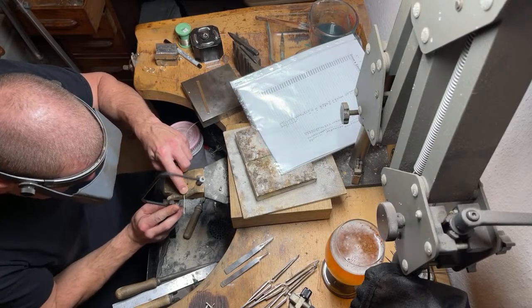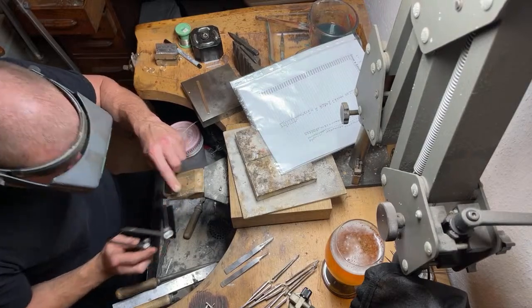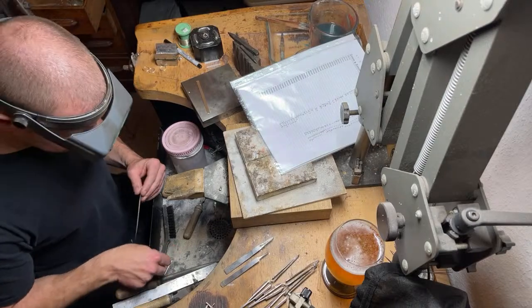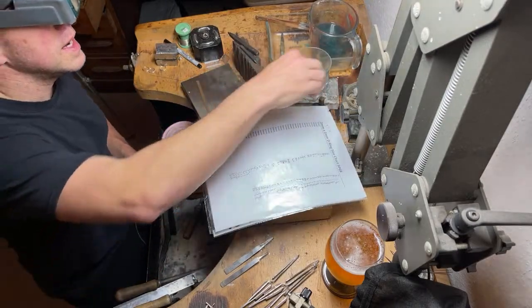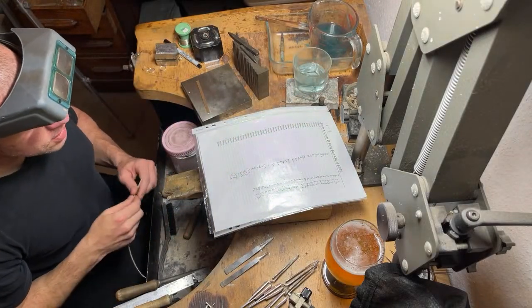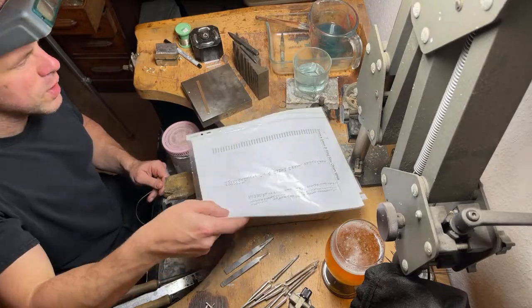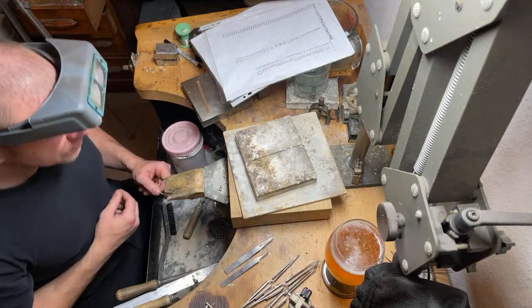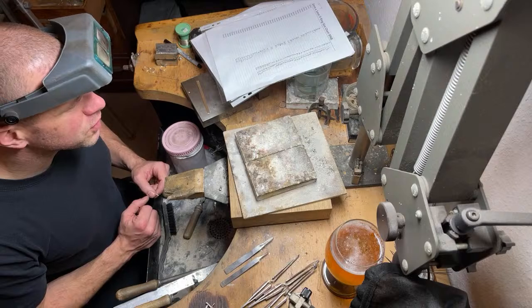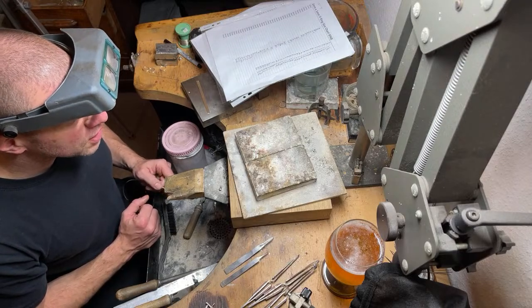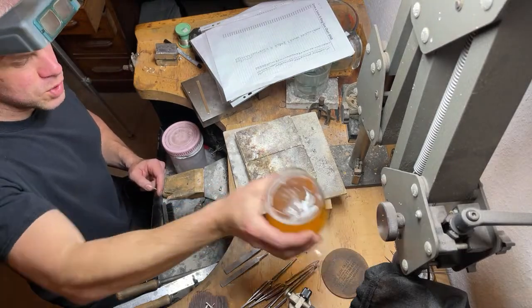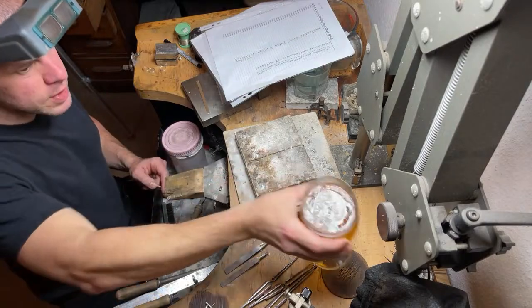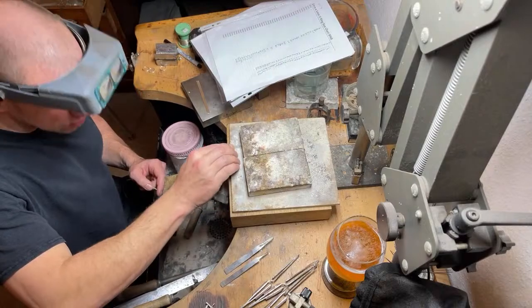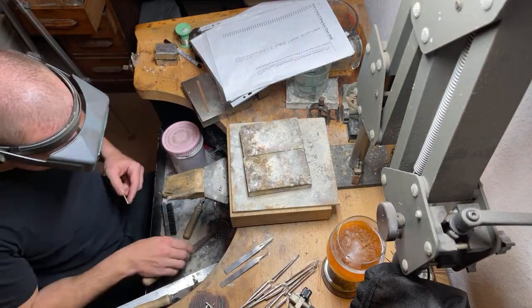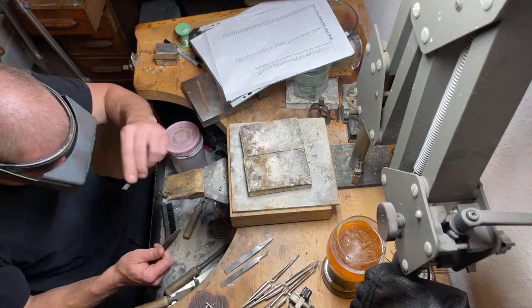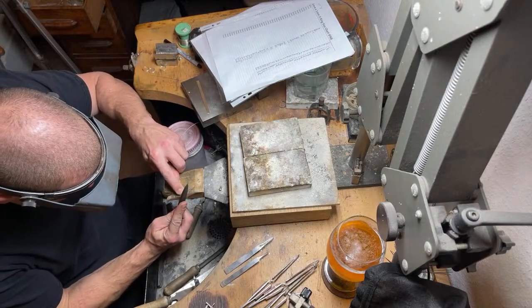What I actually think happened with this, I was quenching it too quickly. It was too hot when I was annealing it. And the funny thing with silver, which I've experienced a few times, is if you quench it too quickly, when you put it through the rolling mills, I wouldn't go so far as to say it's like wringing out a sponge, but I think it takes on some of the water from the quenching subsurface, and then you basically press it out in the rolling mill, which is not good, and it develops porosity, and I think that's what's happening. It's a pretty unusual thing to happen.